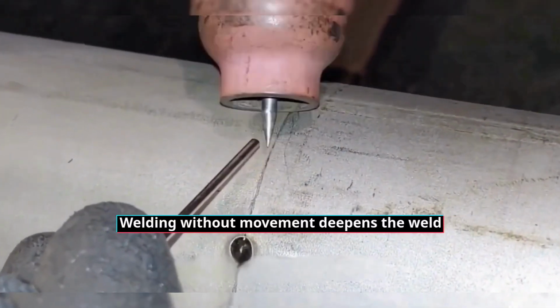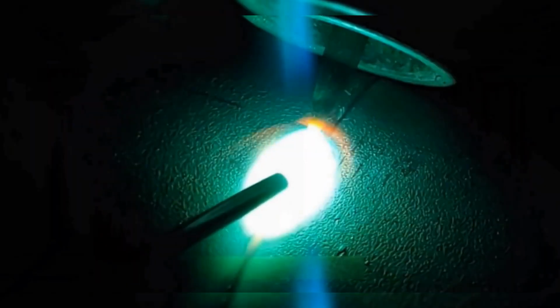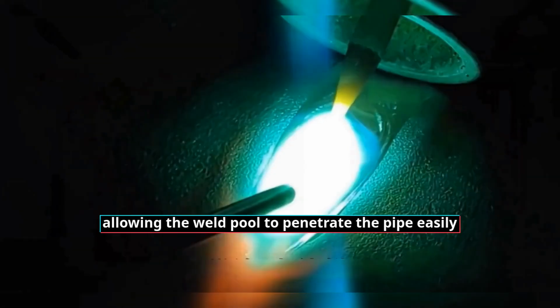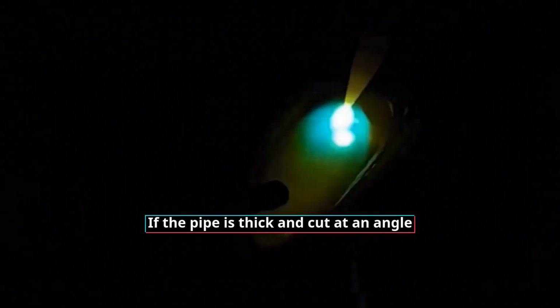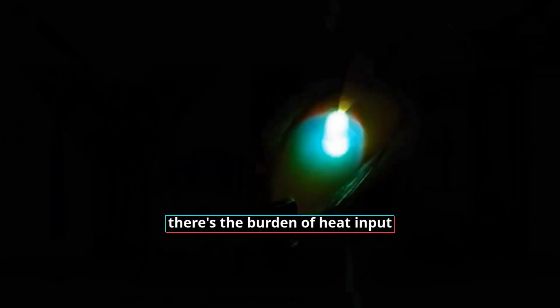Welding without movement deepens the weld pool until it penetrates the pipe. Then the pool's vibrations are minimal, and it's vital to sense the pool's subtle waves. If the pipe is thin or angled, the part's thickness will reduce, allowing the weld pool to penetrate the pipe easily. If the pipe is thick and cut at an angle, passing a thick pipe through the weld pool can be tricky. Plus, there's the burden of heat input, because it requires more heat than a thin pipe.